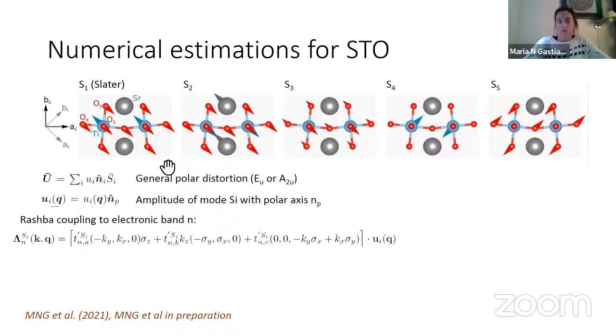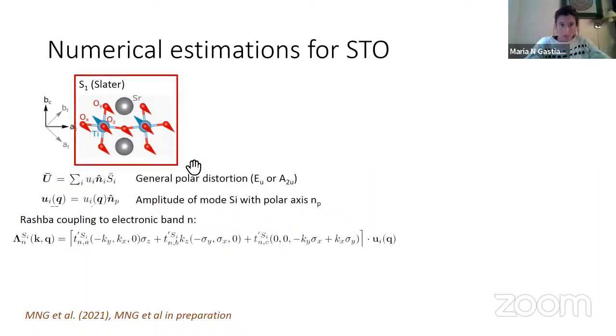So you have some freezing of the mode. Basically, in Ab-initio, what they do is they move the titanium a little bit to the right and the oxygen a little bit to the left, and recalculate the electronic band structure. And from the model that I just showed you, we know that it should couple to linear order in U with this Rashba-like form. So you'll have some induced hopping. Now you are in a tetragonal system, so in principle you'll have two EU components and one A2U one-dimensional component.